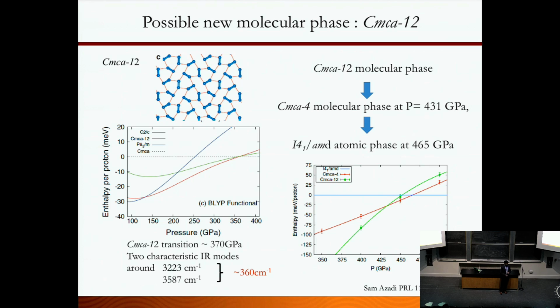And there's some theoretical calculation on alumina under pressure. They predict if you subject alumina to 800 GPa, it can be a metal. So we are at 500 GPa. We are at a much lower pressure compared to the Al2O3 metallization pressure.